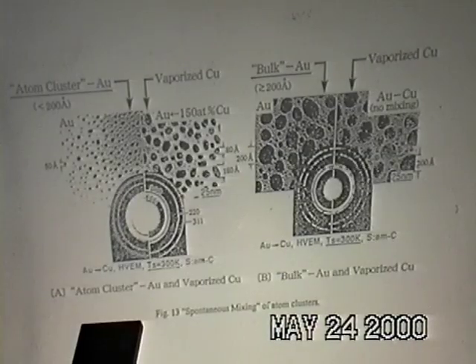You see, copper atoms are instantly dissolved into gold atom cluster in the upper, in which all diffraction rings are expanded, but copper only covers gold particles in the lower, in which diffraction rings of copper only superimpose on those of gold particles. Namely, in the case of FCC metals such as gold and palladium, the critical size is about 20 nanometer in diameter. In short, gold clusters instantly absorb 150 atomic percent, even copper atoms as solute atoms, much more easily than deuterium atoms.